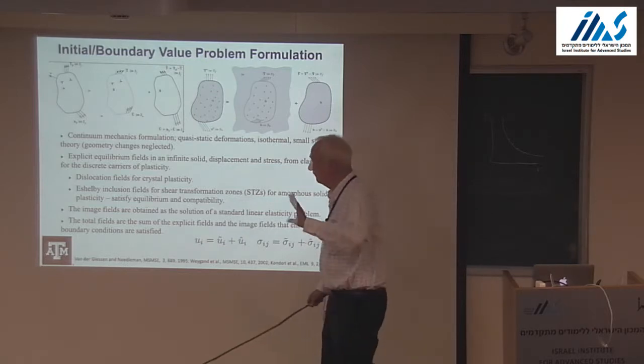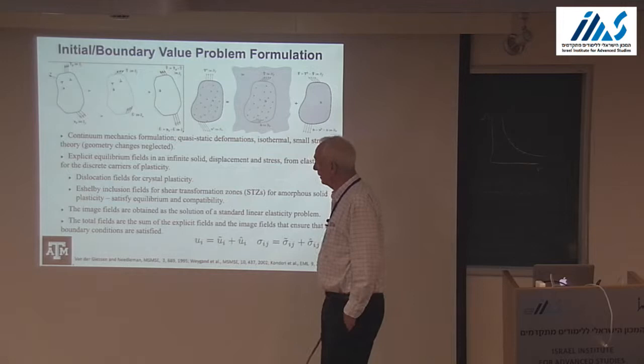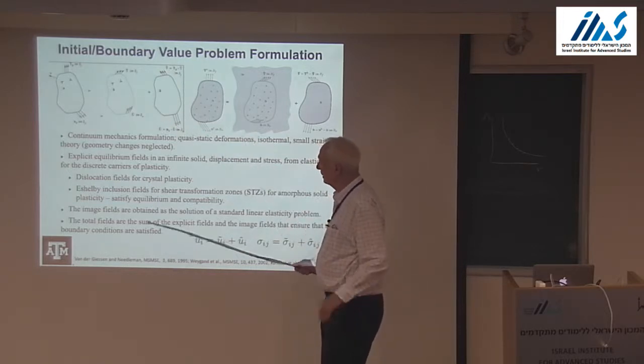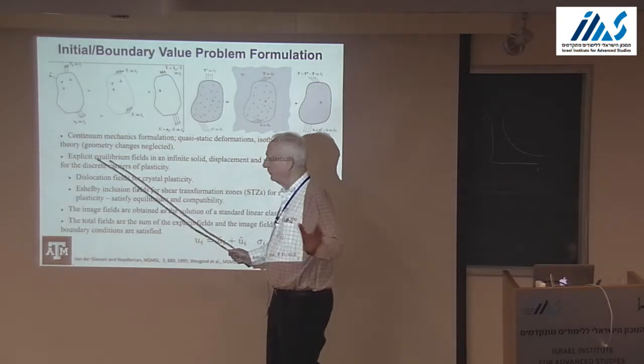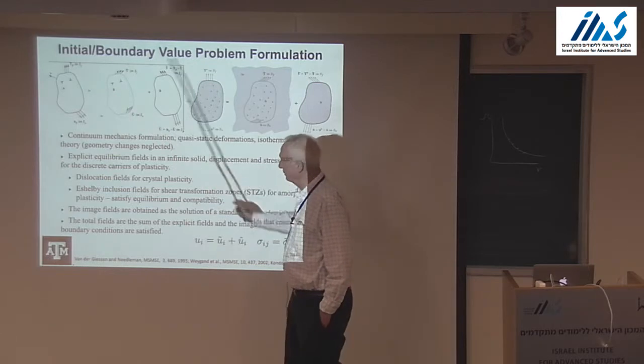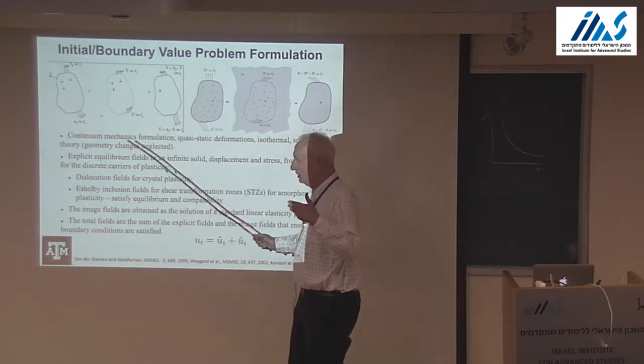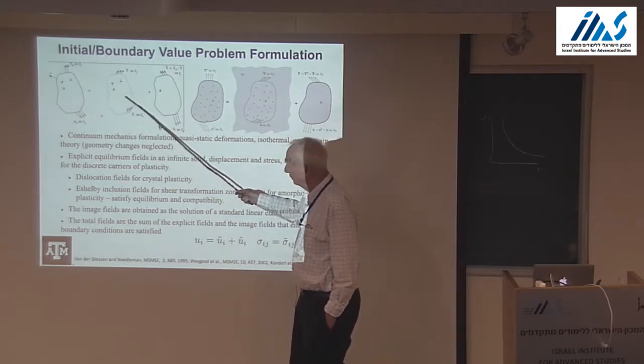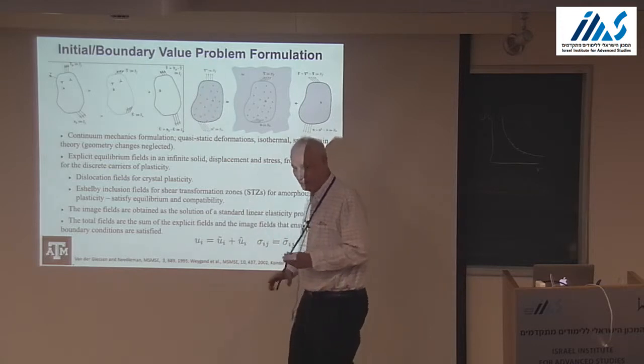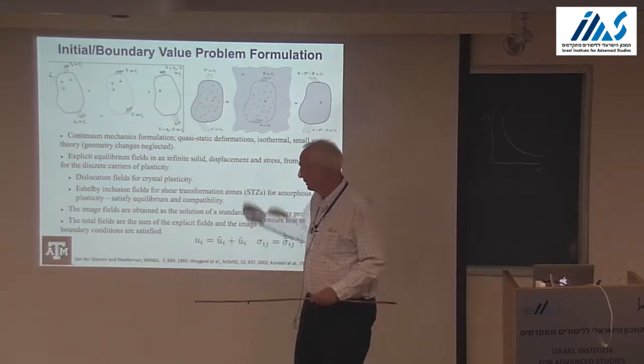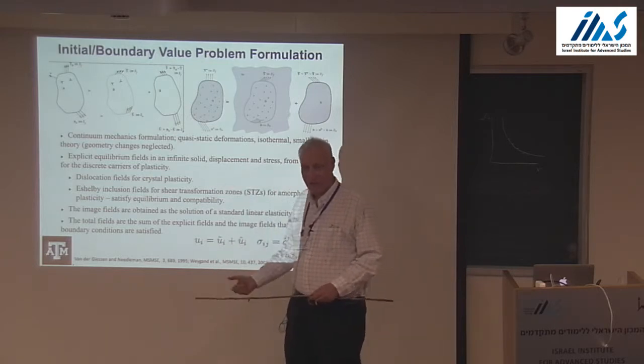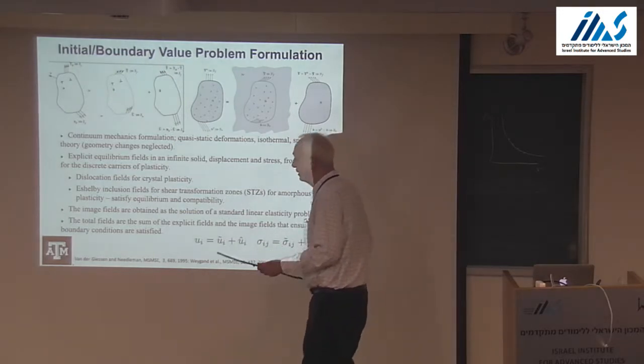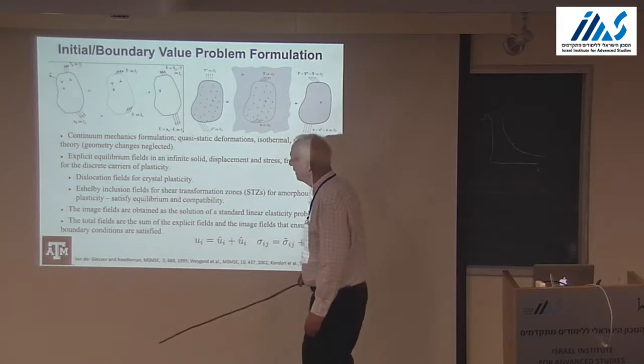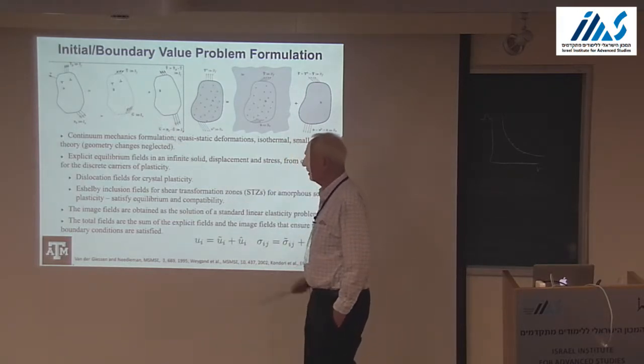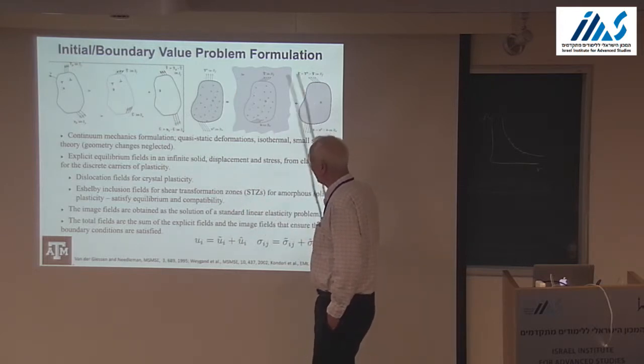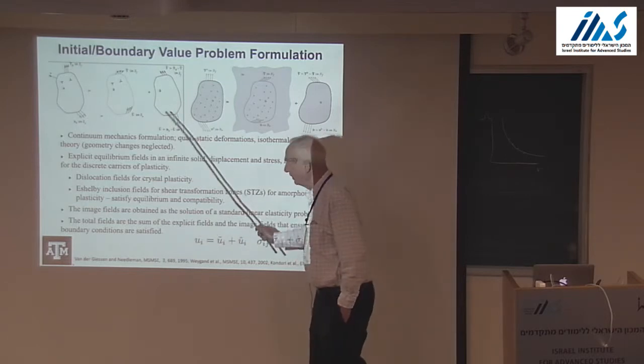Okay, so the approach we're going to take: I do continuum mechanics boundary value problems. We have dislocations or STZs, and we want to solve a boundary value problem for a region. We know these fields analytically, exactly. They satisfy equilibrium conditions, but they don't meet the boundary conditions. So we need an image problem. The nice thing about image problems is that even with dislocations, where we have singularities, all the singularities are outside the region of interest. So we can use a standard numerical method, even if we have 100,000 or more of these, to solve the image problem. And that's what we're going to do in either case, and then use superposition, and we have the solution.